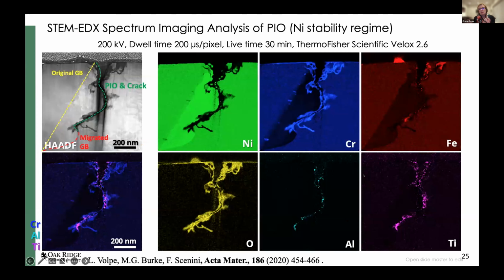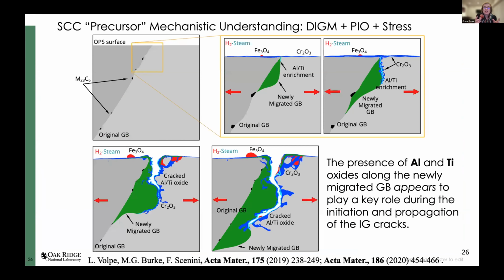And looking at this in more detail in the Talos, we've got very clear diffusion-induced grain boundary migration. Some superposed maps here give a hint with chromium oxide and where the aluminum oxide is located, and titanium oxide. So we can see that those are actually along the center, on the crack itself. So we can get a mechanistic understanding. We've got what's going on and look at how these oxides and the preferential intergranular oxidation is playing a really important role at SCC.